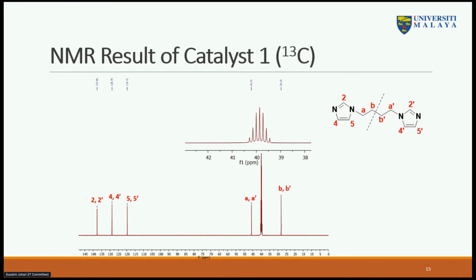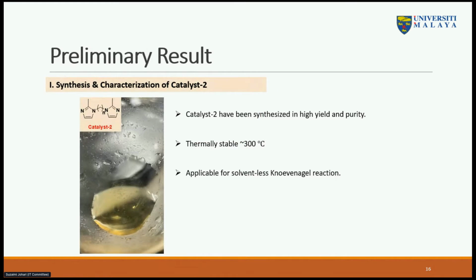So the same also goes for the carbon NMR of this catalyst. It shows very high purity of the compound, with no solvent peaks in this area. And for the synthesis of catalyst 2, interestingly, catalyst 2 was obtained as a liquid, compared to catalyst 1, which we obtained as a solid. But even though it is a liquid, it is also thermally stable until 300 degrees C.